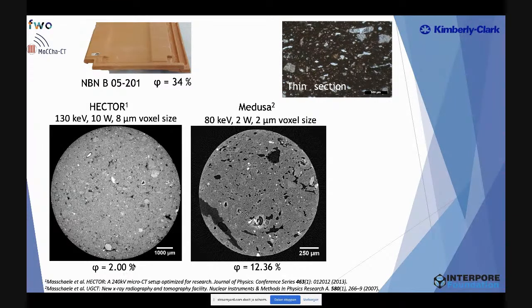If we take an even smaller subsample, something around 1 millimeter diameter, we see more porosity already available, and we have a voxel size here of 2 micron, but still we are missing a lot of the pores below the resolution.